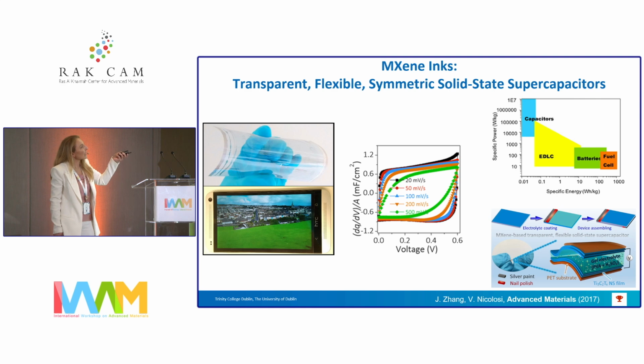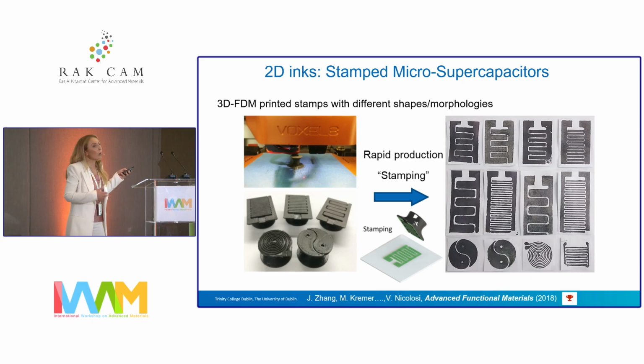Quite astonishing is the rate performance. You can go to very, very high rates, and you still see a quasi-rectangular CV graph, showing basically pretty much no resistive behavior. And we went a step further there. If we have these nice inks, then we can think about prototyping our devices quite fast so that we can test them routinely before we get into cumbersome assembly.